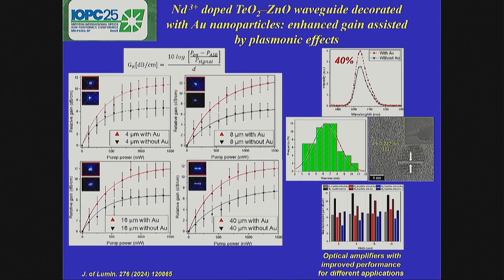In all the cases, we observe the enhancement due to the gold nanoparticles, but the best result refers to the lowest concentration of neodymium, the one in which we used just 1 pellet. Of course, this can be extended to different hosts with different rare earth ions, with different applications for optical amplifiers with high performance.